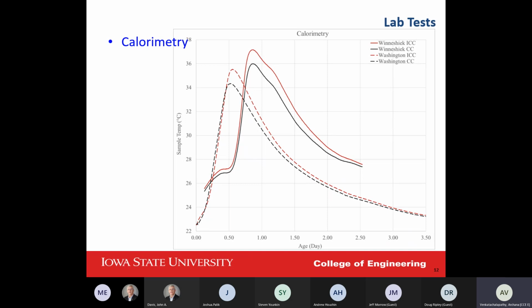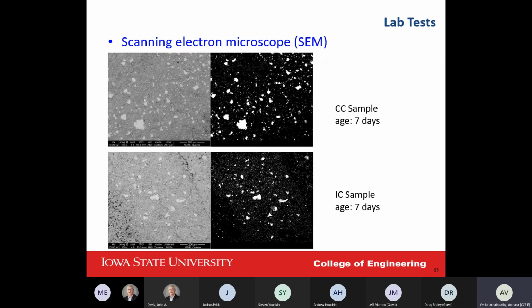As we can see, in the first two days, the higher temperature is very noticeable, because that means the hydration is much higher in the samples with the internal curing method and fine aggregate than in the normal concrete. And that's why the temperature is higher by about 1.5 degrees centigrade.